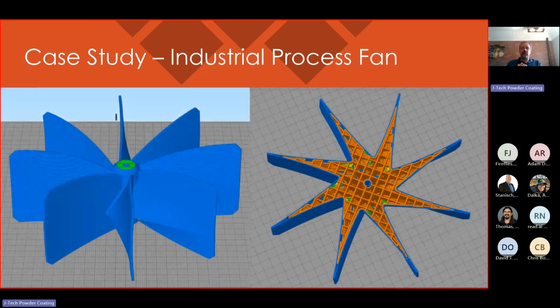Here's the last iteration optimized for a pellet printing application. It will print in about half the time of the original. And as you can see, the blade sections have been thickened for strength. The gussets are blended into the blades, and the blades are curved in 2 dimensions to increase their rigidity. The design flexibility of 3D printing really allows you virtually free added features. Blade thickness was set at 2 times the nozzle width to create a smooth and strong outer shell, and the angles were set so no support material is needed, and the one side is sitting directly on the bed. We have a lot of options to increase strength on this also if needed.